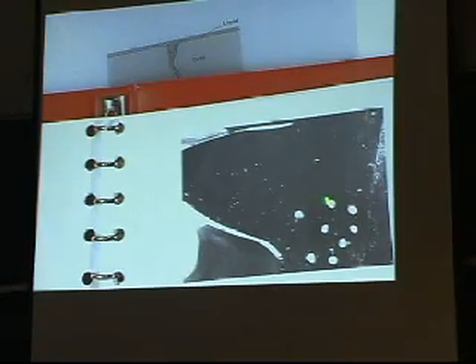Blow that up a little bit. You'll see the crack inside. Now this one's not too hard to interpret, but one of the problems with magnetic particle testing, where you magnetize it, put a magnetic fluid in the steel, or dye penetrant, where you don't have to have a ferromagnetic material, is interpreting things. If I went back to the very first one where I just have a bunch of white dots, are those deep flaws, or are they just surface pits, which are inconsequential? And so often people have to come in and interpret what these indications actually are.